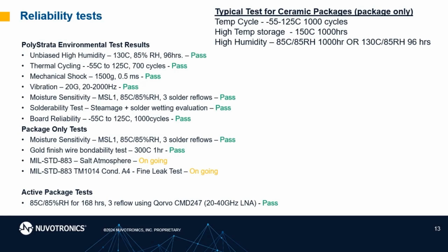Our passivation, our immersion silver, immersion gold finish, we recognize is rather unique on the market, but we have been using it for years for both solder PCB mount applications as well as wire bonding. We've shown through wire bondability tests and board reliability tests that this finish is reliable in both applications. Even after seeing multiple cure cycles or solder reflow cycles, it's still able to retain bondability with high reliability.